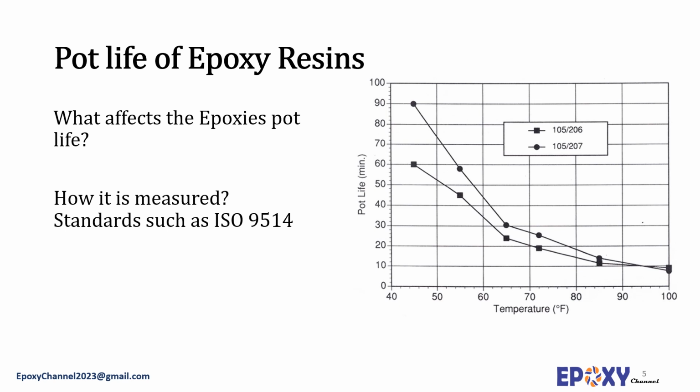Moreover, as the curing of the epoxy coating is an exothermic reaction, or heat generating, the heat will easily build up in the cans and buckets, hence further reducing the pot life. Therefore, pouring it out into a large surface area, such as a paint tray, will slow down the reactivity. However, those treatments might not always work depending on the type of hardener agents used in the mixture. Using retardants, the hardener agents' formulation itself plays an important role in extending the pot life.